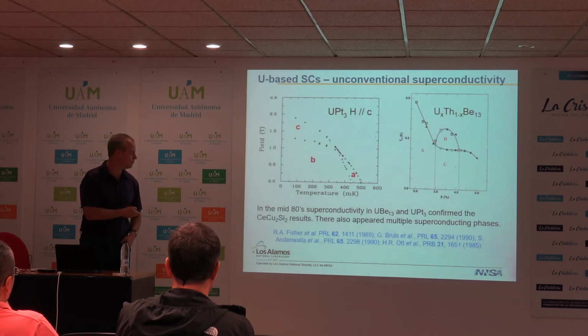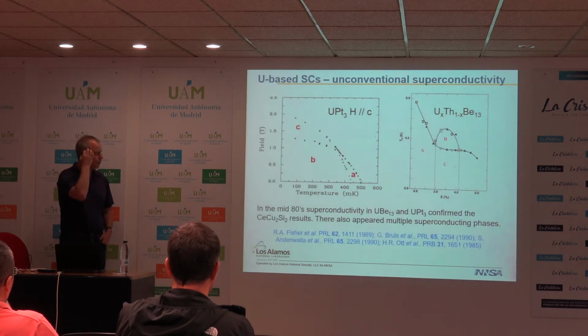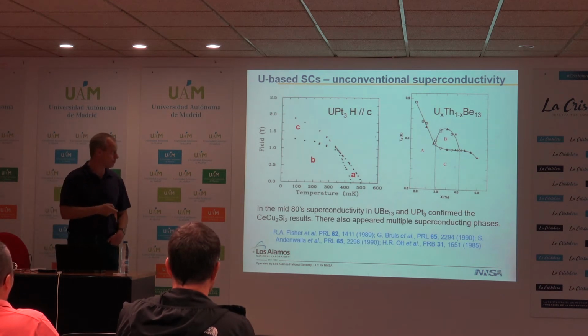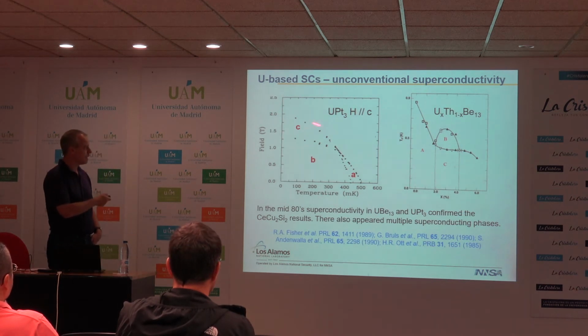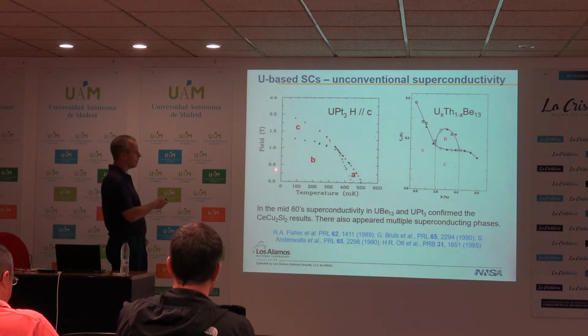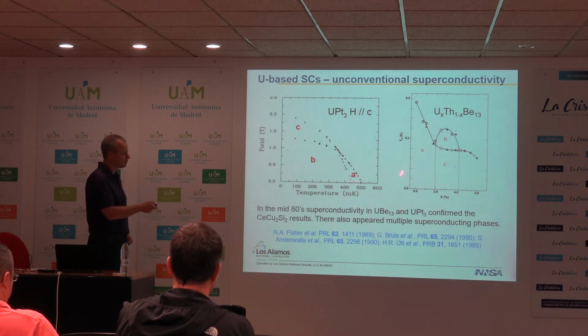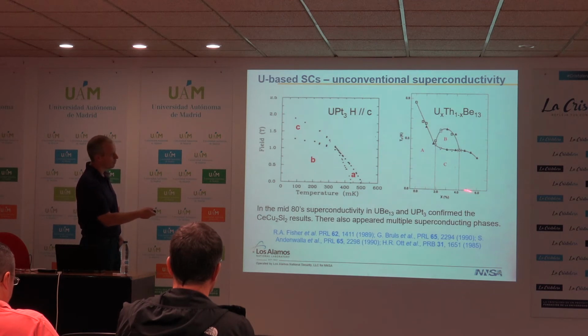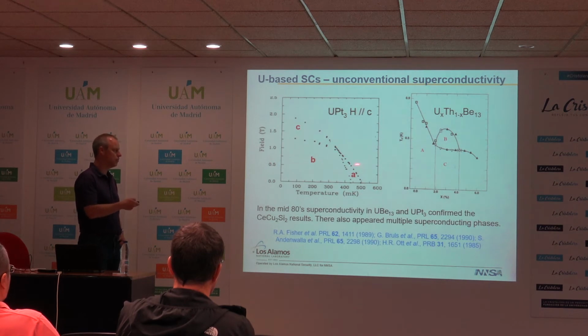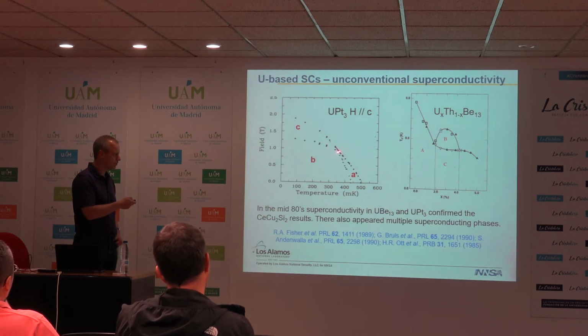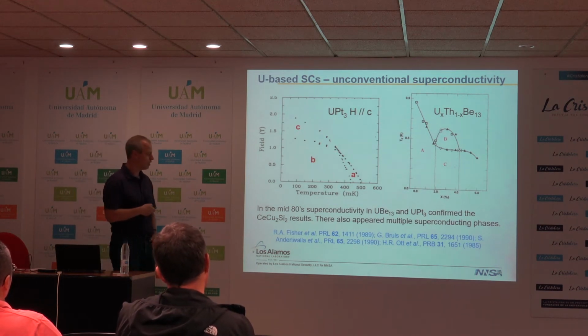However, we will soon realize that this is more of a statement than just the Fermi energy relative to the Debye frequency. And this came a few years later when the discovery of superconductivity happened in a few uranium compounds. So here is work on uranium platinum-3, as well as uranium beryllium-13 doped with thorium. And what is very striking about these phase diagrams, now this is magnetic field as a function of temperature, this is temperature as a function of doping with thorium, you see multiple superconducting phases. So in UPt3, famously, it has 3 superconducting phases. They seem to all converge at a single point here in the phase diagram.